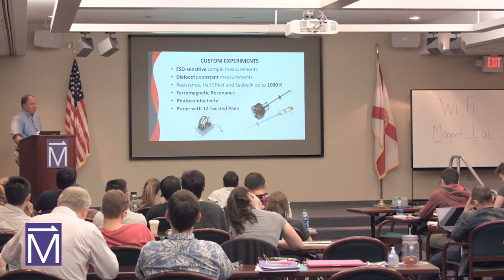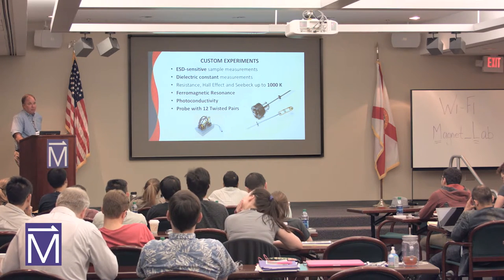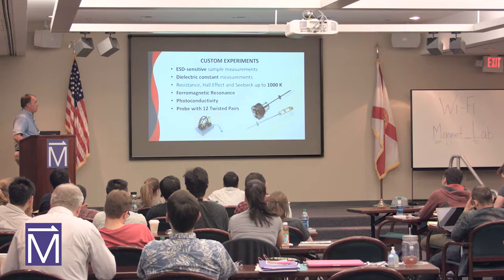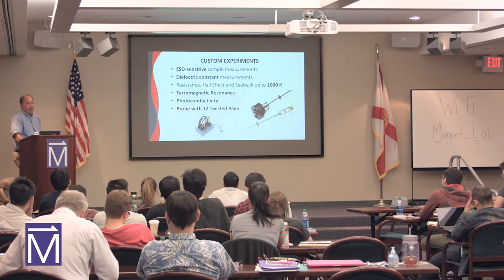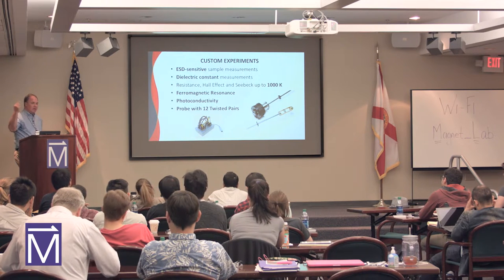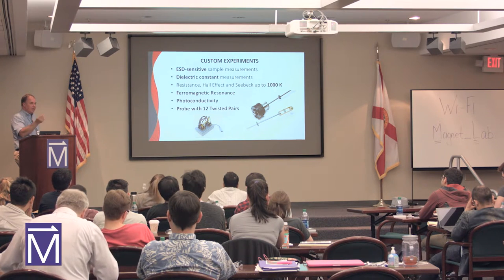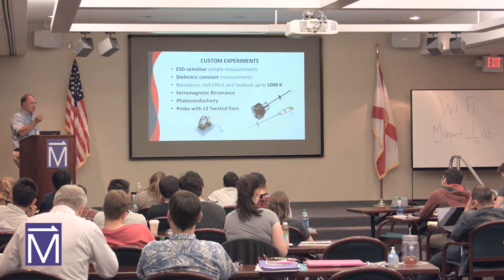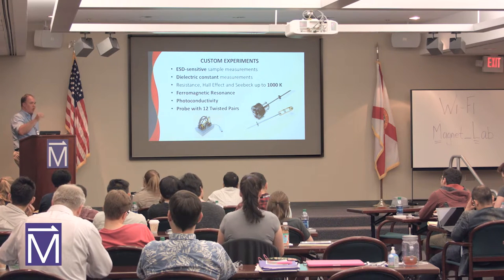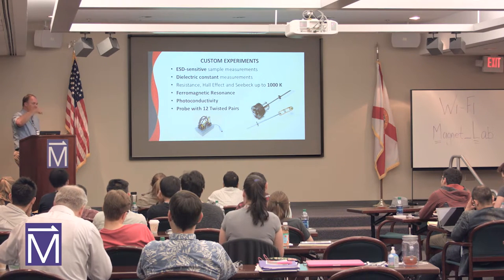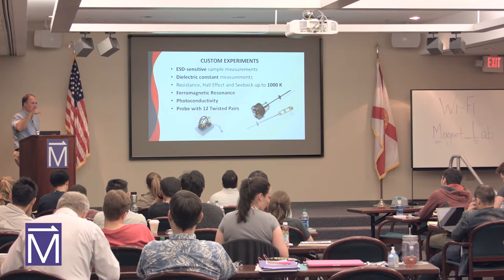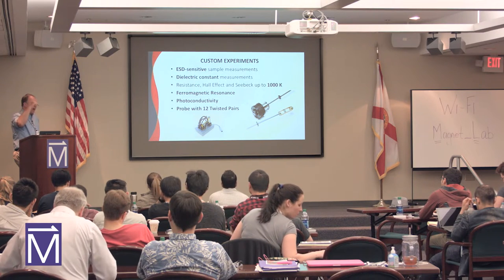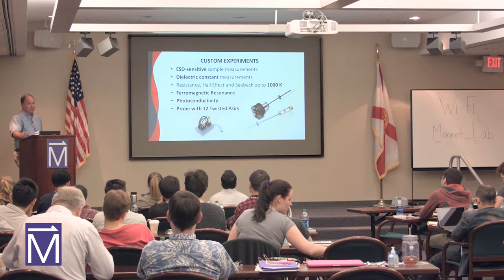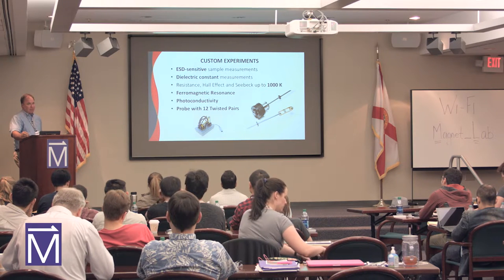We essentially use what we call a multifunction probe. You can purchase a bare probe that you can wire up through the top of the sample space. So it can still plug into the bottom of the physical property measurement system connection, or you can eliminate that entirely. You can still use part of those wires to your sample, but you can run your own wires to your sample for these ESD graphene type samples.